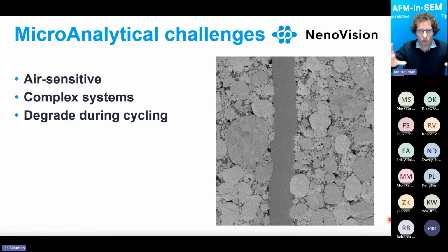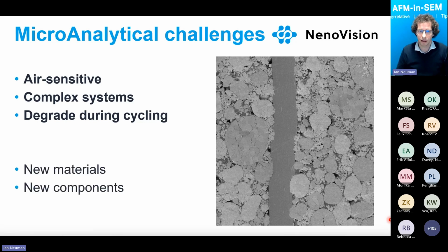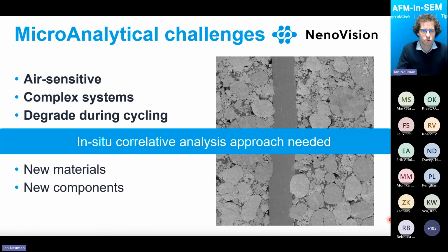So if we go from the macro analysis, now we dive into the micro analysis. I would like to point out that battery materials are not the easiest to measure. Many of you, I believe, are very experienced. Why? One point is they are very air sensitive because of the lithium, so any air exposure may affect and complicate the further analysis. We talk about a complex system, about the anode, cathode, electrodes degrading and changing during cycling, and also new materials, new components and new structures are coming in and are studied. So here we believe that an in situ correlative analysis approach is simply needed to be able to understand what is going on and what the properties of our materials are.